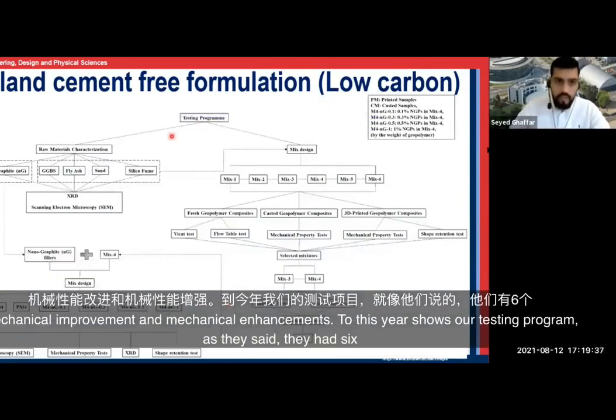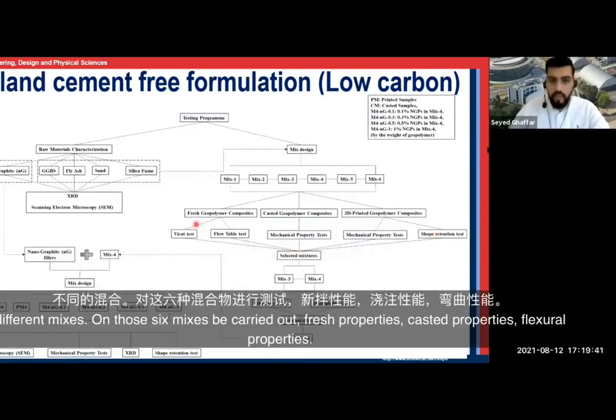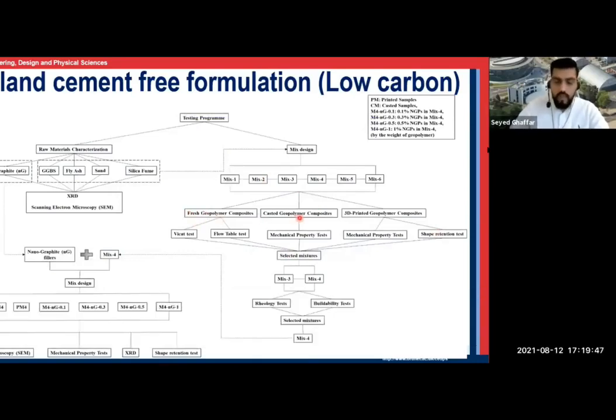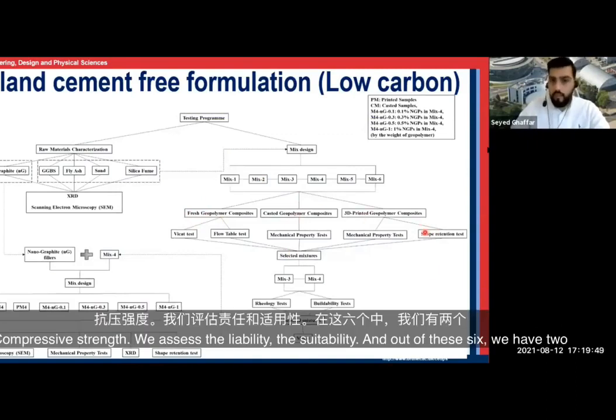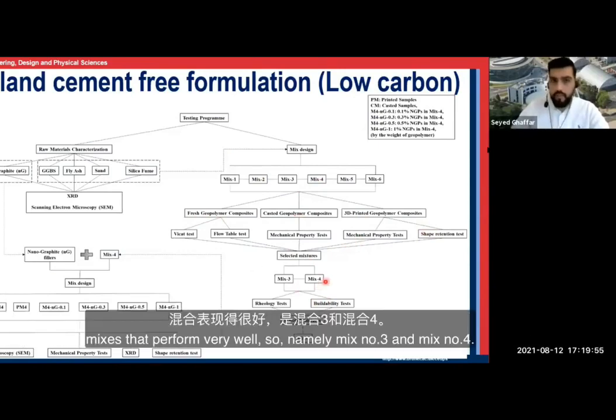So this here shows our testing program. As I said, we had 6 different mixes. On those 6 mixes, we carried out fresh properties and hardening properties, so flexural strength and compressive strength. We assessed the bendability, the extrudability, and out of these 6, we have 2 mixes that performed really well.